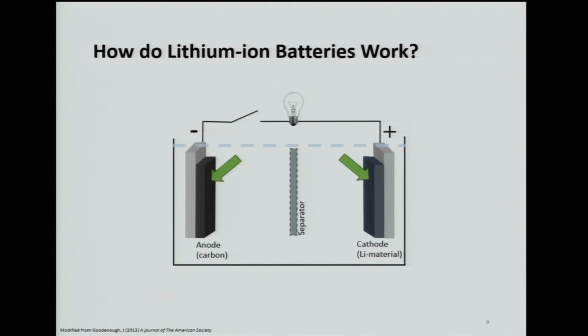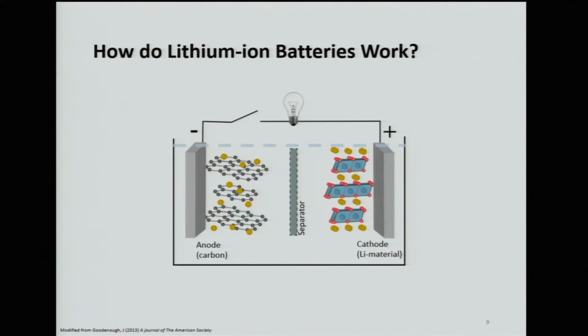Now, with lithium-ion batteries, the electrodes are composed of coatings on top of a metal surface. And this coating composition will vary depending on whether it's an anode or a cathode. Anodes are usually composed of carbon, and the cathode is usually the lithium-ion material. Now let's look at these coatings on a molecular level. The anode is composed of carbon atoms arranged in a honeycomb structure, and we have layers of it. The cathode is composed of lithium-ion layers and a matrix, and this matrix composition will vary depending on the type of material that we're using.